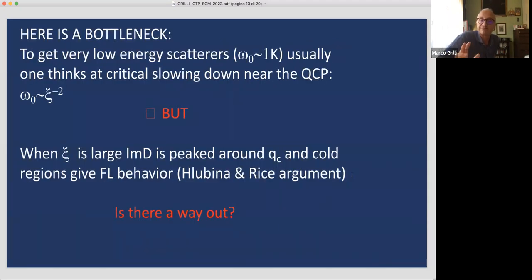So we are facing now a bottleneck, because on the one hand, to have a very low energy scatterer, which can explain linear resistivity down to a few Kelvin, we need very low energy. And therefore one is tempted to use a very large psi, so to approach the quantum critical point and take an increasing psi. But if we take a large psi, then the interaction becomes peaked around QC, and therefore it is no longer isotropic, and the Hlubina and Rice argument kills us, kills the strange metal behavior. So what is the way out?